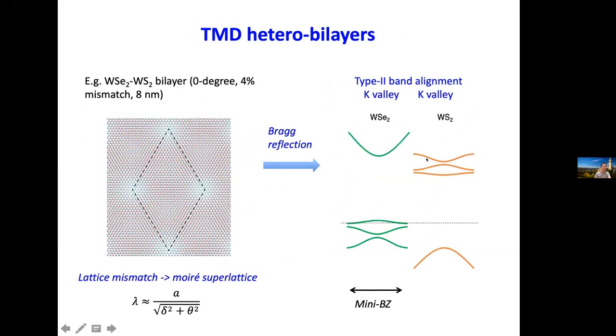So when the twist angle between the two layers is small, a moiré pattern is formed. And for this pair, the lattice mismatch is about 4%, and that gives a period of about 8 nanometers at 0 or 60 degree twist angle.